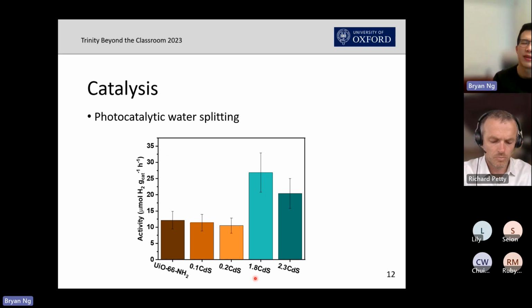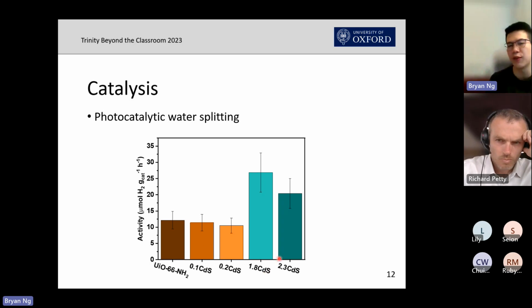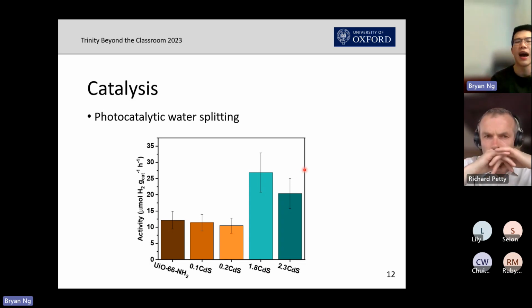Now, I found out that there is an optimal point that I can add to. If I add even more cadmium sulfide, it actually doesn't give a very good rate. But at 1.8% of cadmium sulfide, I would be able to get very good results on catalytic activity. So then I will need to do some characterization in order to explain what exactly is happening inside this system.